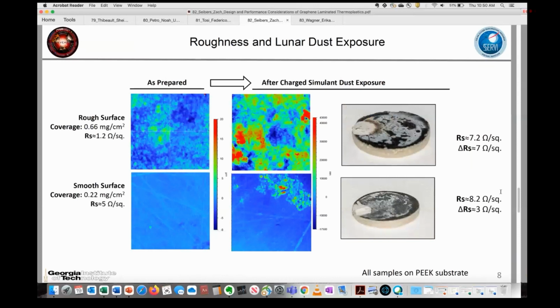After we expose these to charged simulant dust, we see dramatic changes. And I'll add that these surfaces are certainly on the rougher side. We wanted to try and tease out a result here, but there's a big difference in the roughness, as you can see by the profilometry of the starting condition. That being said, when we expose these using the exact same exposure cycle, we see dramatic differences in how much dust is retained in the surface. And we don't see huge differences in the sheet resistance, I will admit that. However, I think the profilometry scans here are pretty telling, as well as the images. You can see that the rougher surface generates a white, thick, cake-like coating in areas, whereas the smoother surface is much better at getting rid of that.